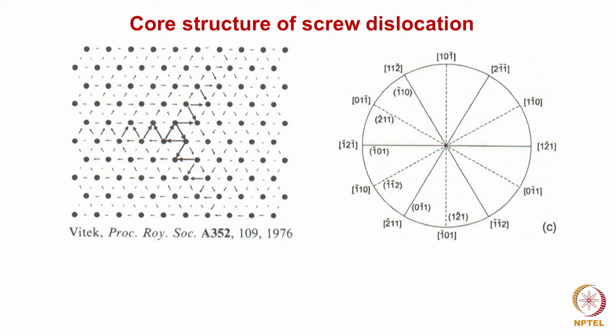And we know that around the dislocation line direction, now we are looking at how the displacements of the atoms are taking place. They are being shown by arrows. So after these computer calculations, they marked the positions of atoms on the 110 plane, and with the dislocation core at this center, how the displacements are taking place.